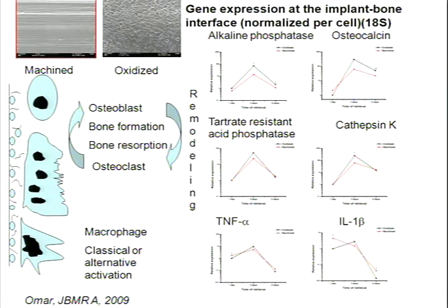Alkaline phosphatase and osteocalcin, two genes that denote bone formation. Very rapidly, we have a triggering of those genes within hours at both types of surfaces, the smooth surfaces and the little bit more rough surface. However, there is a difference. One of these surfaces, the more rough, there you have a stronger expression of bone formation. Very interesting. How come?